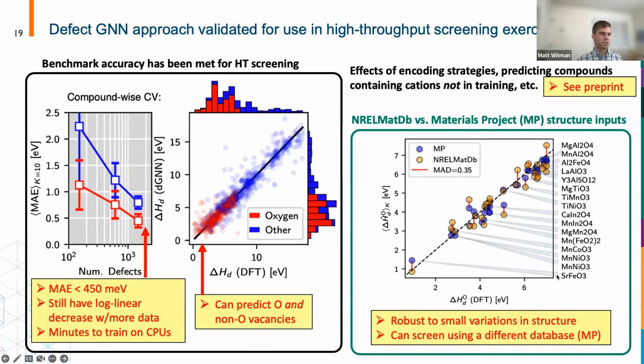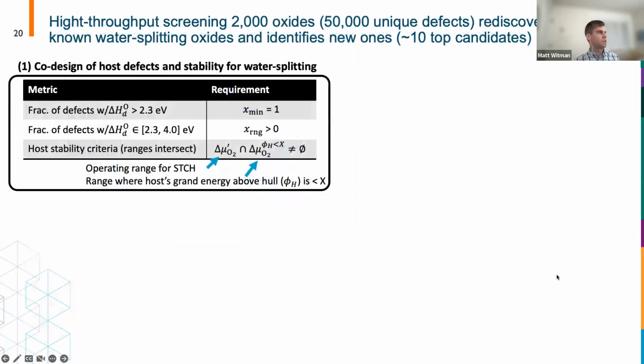So we went ahead and used this to screen the Materials Project. We high throughput screened a bunch of metal oxides and rediscovered some known water splitting oxides, and of course identified new ones that we're going to now test in lab. So again, I mentioned we're looking for this requirement that all the defects are above some minimum threshold, and then at least one is in this critical range, but in reality, you'd probably want all of them to be in this critical range. And then the final key down selection criterion is that we have a target chemical potential range of oxygen that's defined by the STCH process.